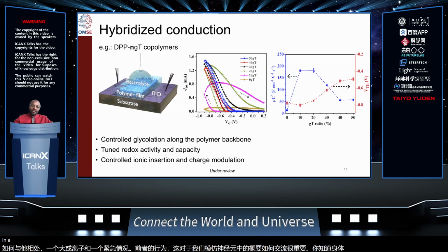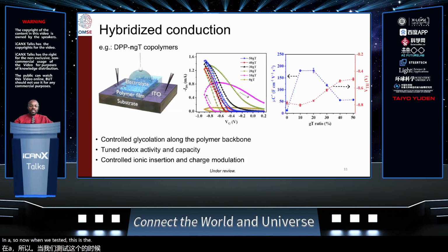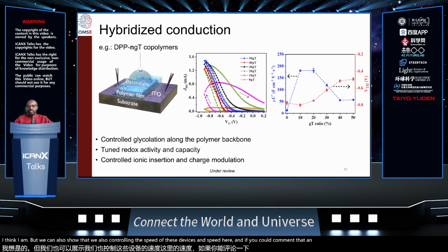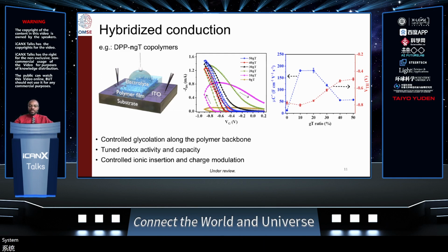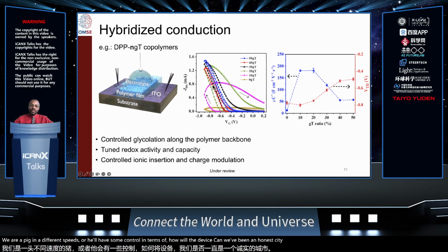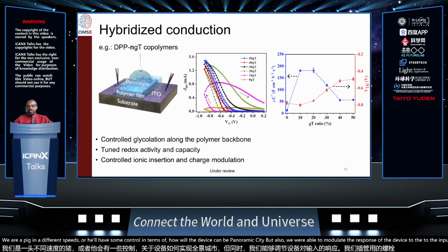Now when we test the transistor devices, we can see that not only are we determining how well the device is able to uptake ions, but we're also controlling the speed of these devices. Let me quickly comment that in biological systems, speed is important because different analytes and different metabolites are released or uptaken at different speeds. So we have some control in terms of how well the device can retain ionic species, but we were also able to modulate the response of the device to the input voltage, where the input voltage translates to the amount of ions that we inserted.